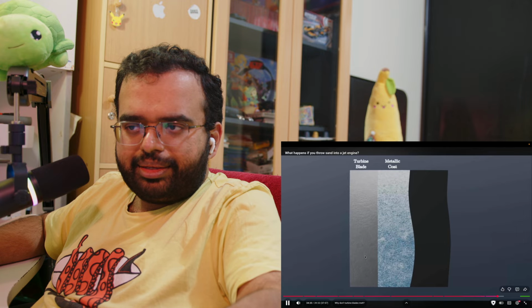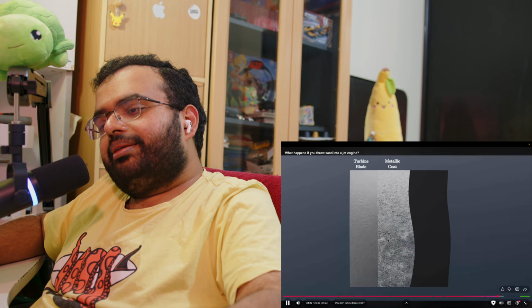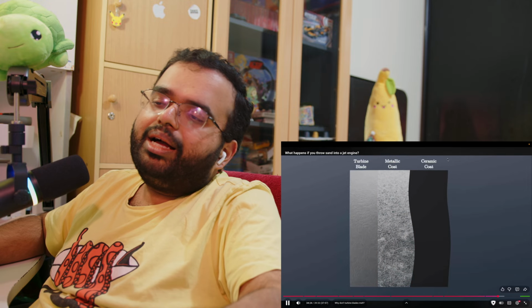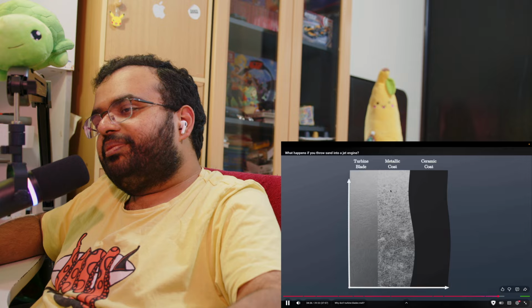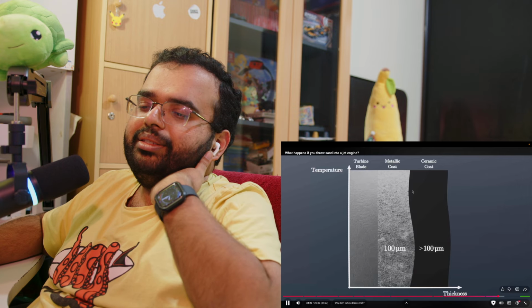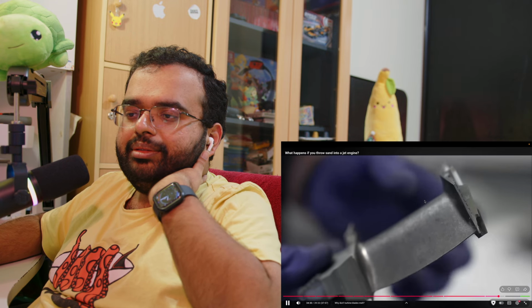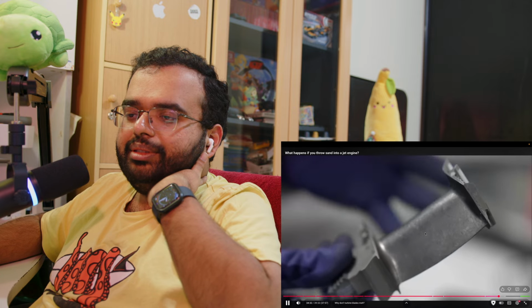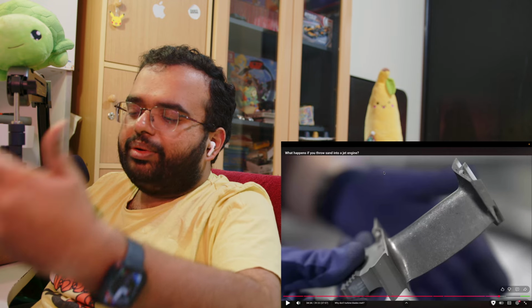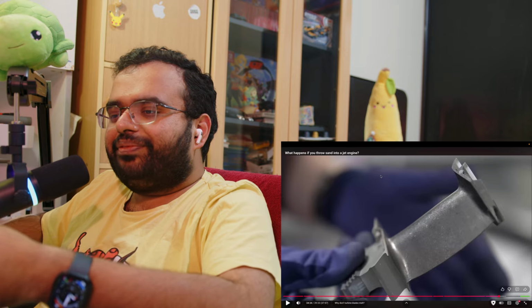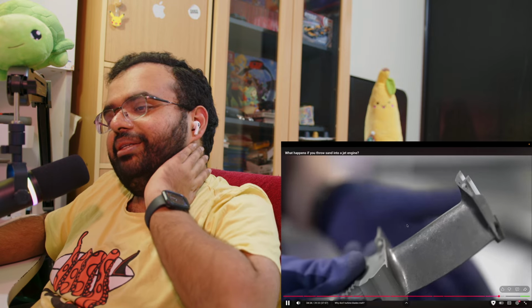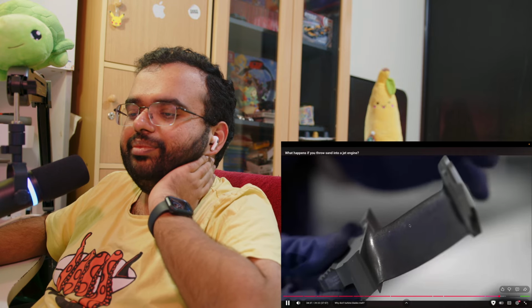First, a thin metallic bond coat that resists oxidation. And then a ceramic top coat. Even though it's only about 1/4 millimeter thick, this ceramic coating can keep the metal beneath it 100 to 170 degrees cooler than it would otherwise be. And I'm guessing that combined with the air holes, it's just enough to make sure they don't melt. And this is the final barrier that stops the blades from melting.